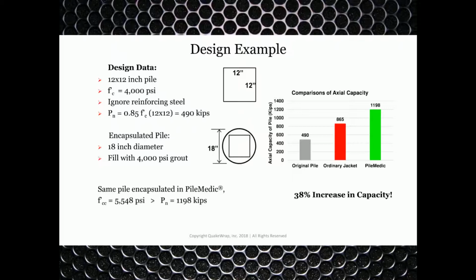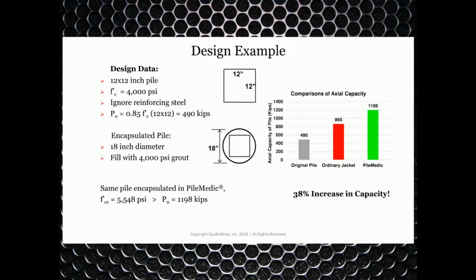If we wanted to increase that capacity, we could put an ordinary jacket on, 18-inch diameter, filled with 4,000 psi grout, resulting in about an 865 kip capacity. The same pile encapsulated in PileMedic results in about 1,198 kip capacity. So that's about a 38% increase in capacity compared to a conventional jacket.